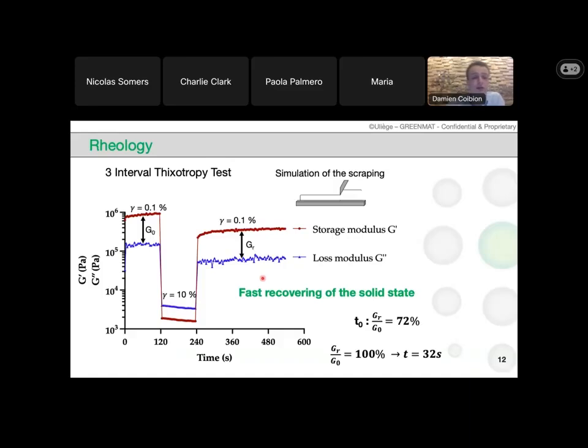So the next analysis that we are performing on our paste is the 3-interval thixotropy test, which is used to simulate the scraping. In this graph, you can find 2 sets of data. The first one, the red one, is the storage modulus. We can say also the solid modulus. And the blue one, which is the loss modulus, can be compared to a liquid modulus. So the graph is separated in 3 zones. The first one corresponds to the steady state of the paste inside the 3D printer. There is almost no shearing on the paste. And what we can see is that the storage modulus is above the loss modulus. It's almost 6 times, I think, higher than the liquid modulus. So at this stage, we have a more solid state of the paste. So the paste will not flow by its own on the plate.